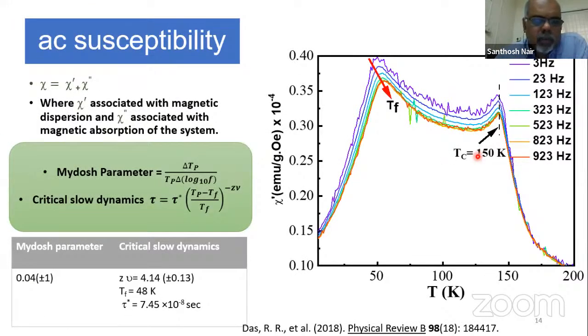The other way to look at this is by doing an AC magnetic susceptibility. So you have two peaks here, one at 150 K corresponding to what we call a ferromagnetic system. The other one is at the lowest temperature. At the high temperature 150 K, with different frequency, the peak doesn't shift, which shows it's not a glassy transition, but the low temperature transition actually shifts. And we can analyze this curve using a critical slowing down model or the Vogel-Fulcher model, and looking at the Mydosh parameter, which looks at the peak shift with respect to the frequency. All those parameters basically tell you that you have an interacting magnetic glass, or what you call a clustered glass system.